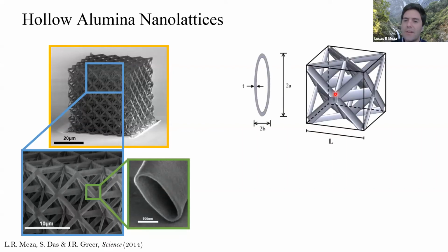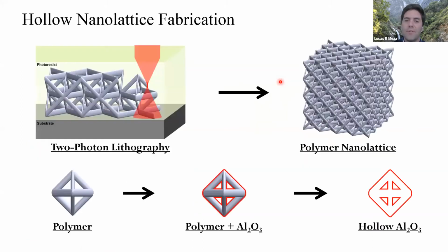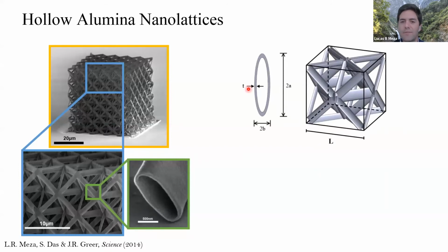So this is a cut section. This is an octet truss hollow. Again, you have the size of the structure, the aspect ratio. Unfortunately, as a byproduct of the fabrication process, you end up with an elliptical cross section — two-photon lithography gives you an ellipsoid as your unit, which is not the end of the world, but it is what it is. You can build it up to make circular structures, but then you have larger features, and the mechanics change slightly. I can talk more about that if anyone's interested.